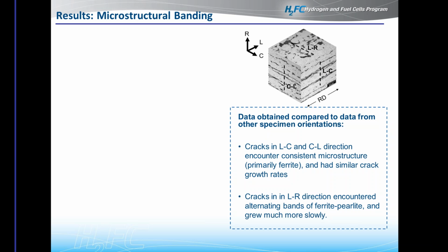The LR orientation, as you can see on the top of the cube, is now propagating through these layers of ferrite and pearlite. So in other words, they're alternating layers. Although a banded microstructure is far removed from what we would call a technologically optimal microstructure, we can use the fact that we have this pipe, or this material, in our hands and do testing, which will allow us to really see what the effects of microstructure are, at really different extremes.